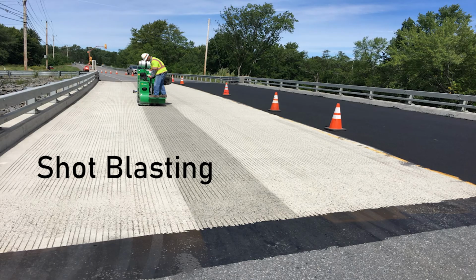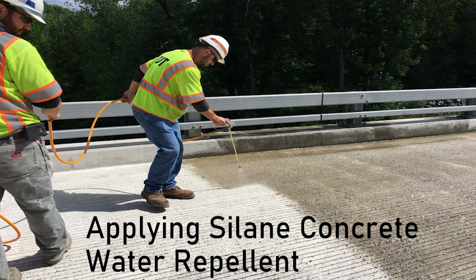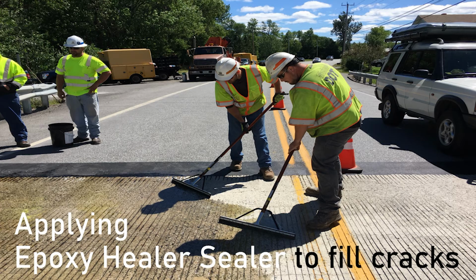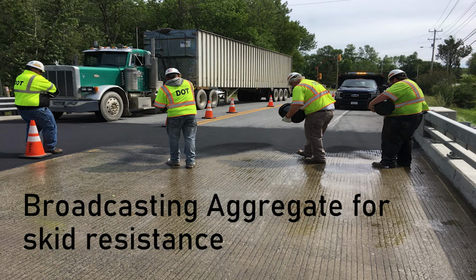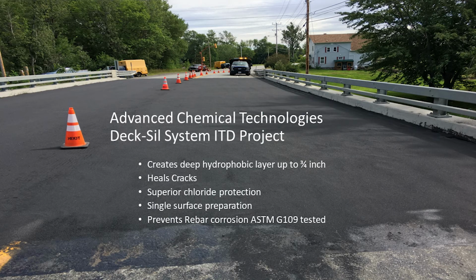The first step is the shot blasting of the area. Then after that, they spray the Silane on the structure, on the concrete. The following step is the application of the epoxy healer sealer to fill all the existing cracks in the concrete. After that's done, they broadcast the aggregate for the skid resistance, and the project is done. So this is a different way of doing that, and brings a lot of value and durability to the concrete structure.